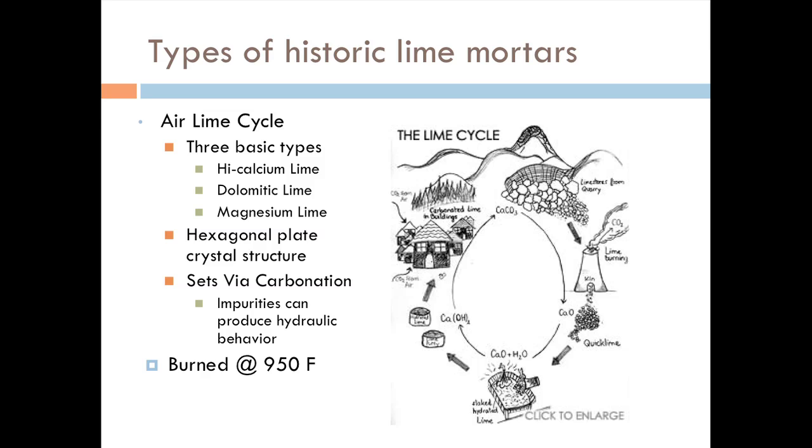If you ever look at a mortar, you can see little blips or little nodules of white. Most likely, that's an imperfection in the mortar mixing, and that would be an indication of a pure lime mortar, especially in any building built definitely before 1818 in the United States, probably even in this area, all the way up to the early 20th century.